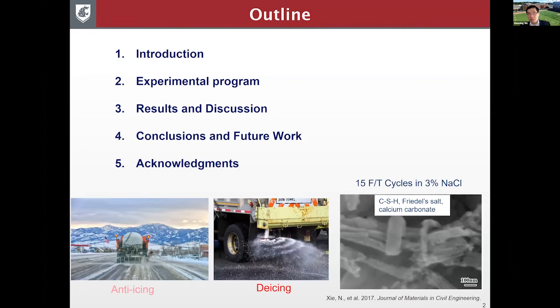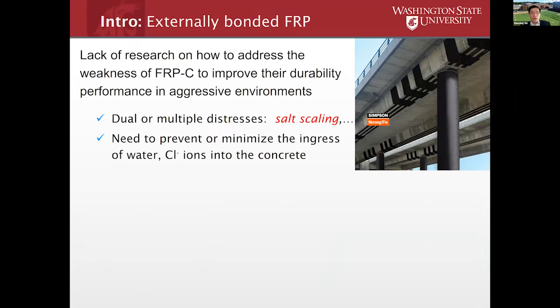So basically, you are seeing calcium leaching out of the concrete or the CSH gel, and the formation of some expansive crystalline phases inside the concrete, which can cause cracking and increase permeability. So one of the tools in the toolbox is the externally bonded FRP fabric. You can see this photo was adopted from Simpson Strong-Tie, illustrating how we use FRP after seismic damage or for the need of repair, retrofit, or strengthening.